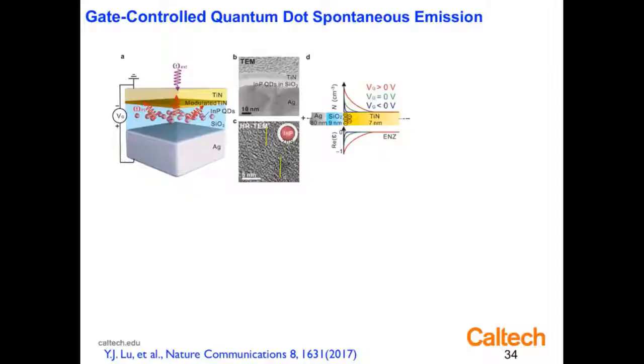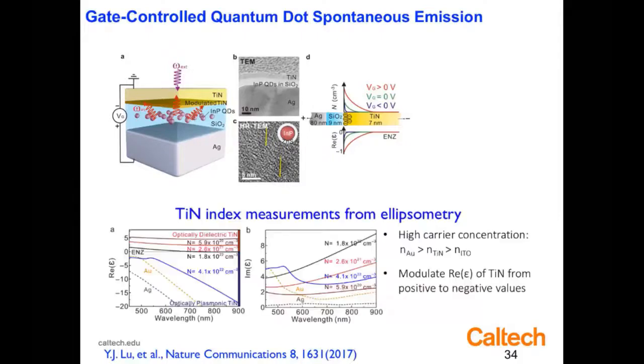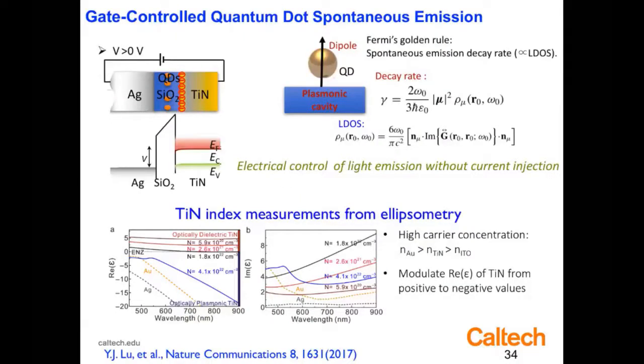So you can see here that if we change the optical environment, the so-called local density of optical states around this, we change the permittivity of the titanium nitride. There's a lot of detail here, but basically applying the voltage, we can change the permittivity from near zero to highly negative, from near resonance to quite metallic in this frequency range. And what we know is that the emission rate, the number of photons emitted into the far field, is proportional to the optical environment, the so-called optical density of states or mode density. And we can change this by changing the permittivity.